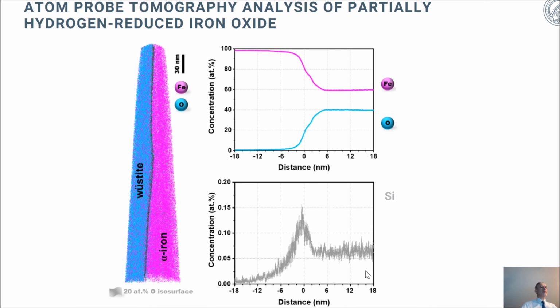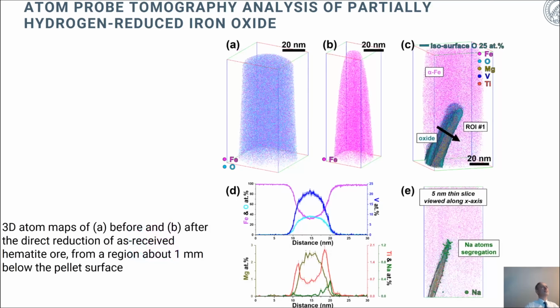What is also very important to see here, however, is this very high buildup of silicon, which is deposited on this moving interface, which would obviously make the motion of the interface during the last step of the reduction much more sluggish. So the take-home message from this picture is that we also have to consider the impurity drag, so to say, on that interface as a function of the reduction.